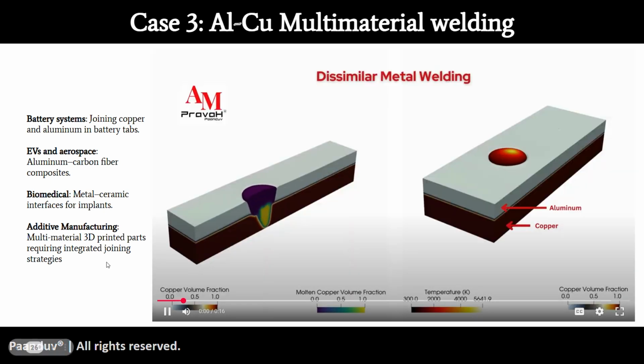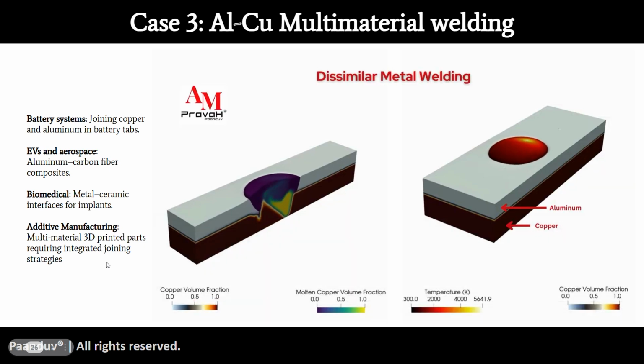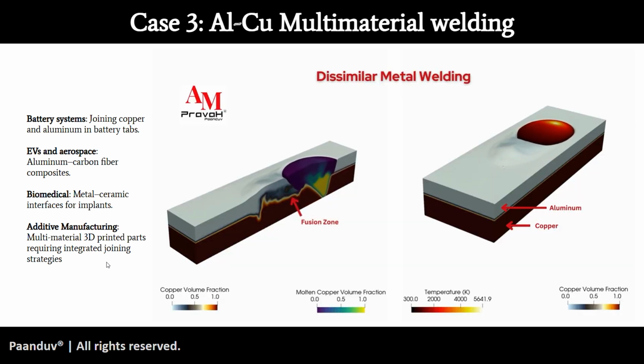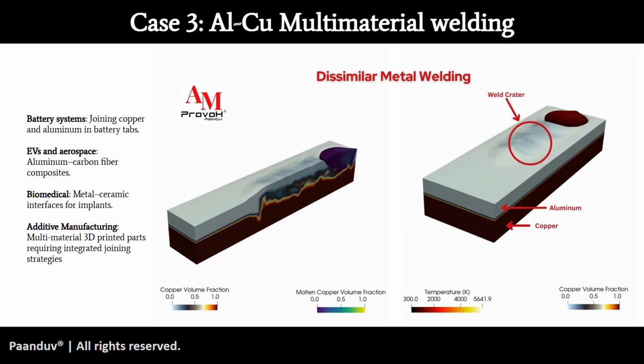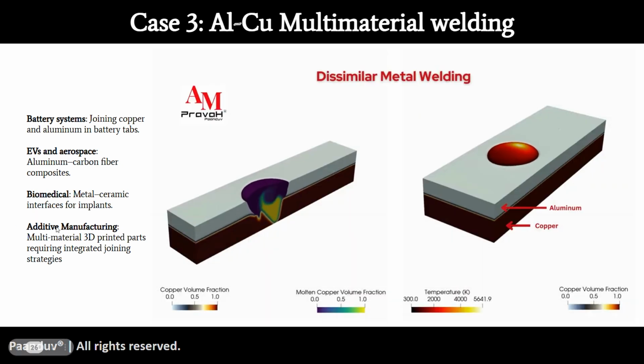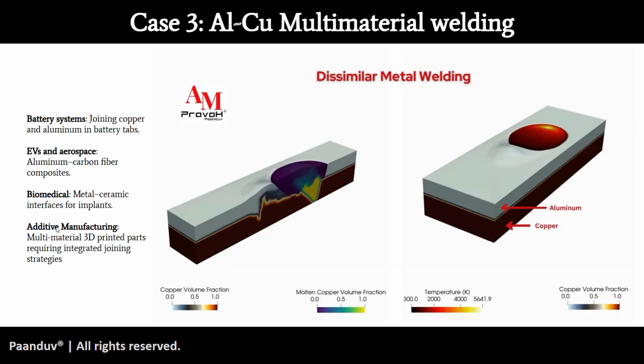The third case that I want to talk about is aluminium copper multi-material welding, a relatively new development in our team. I want you to appreciate that here the number of phases is quite huge. There's a copper solid phase, a copper melt phase, an aluminium solid phase, and an aluminium copper phase, and then a laser is being shot down, first penetrating the aluminium phase and then penetrating the copper phase. And look at the fusion of this interface, how nicely copper is fusing into aluminium, solidifying, and a little hump is formed. If you look at the right image, it is also called a weld crater.